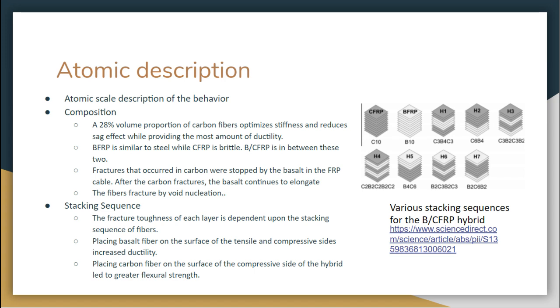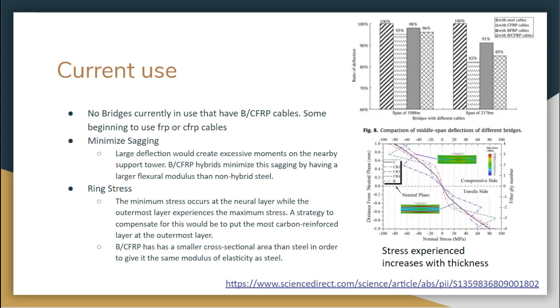So an example of how composition and stacking sequences affect hybrid cables can be seen in the behavior of fracture of these different hybrids. So in some hybrid cables, we see that cracks that propagate through carbon fiber don't necessarily go through the basalt fibers. This is because of the ductility of the basalt fibers compared to the brittleness of carbon, where crack propagation is easier. These fractures that stop at basalt also help to strengthen the material, and it made sure that the material was still ductile as there was load applied on it and being deformed.